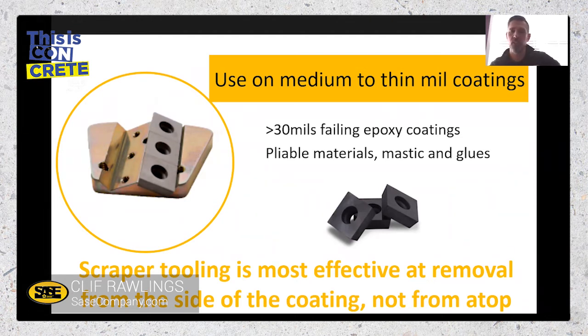So again, let's say you have a thick cure and seal, and the customer says I want a Class A exposure like a salt and pepper. They don't want to see aggregate. This would be a good option to run over it first, or chemically strip the cure and seal, and then you don't have to cut with a really aggressive metal bond to cut the rest of it off. You could go with something much lighter, a higher bond, and remove the remainder, then the film that's left behind, and then give your customer that salt and pepper or cream finish that they wanted in the first place.